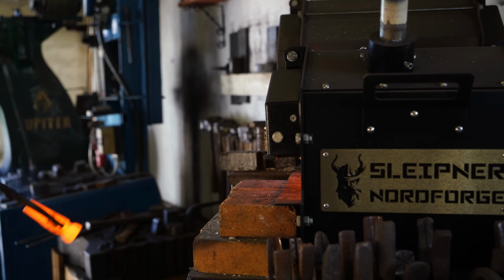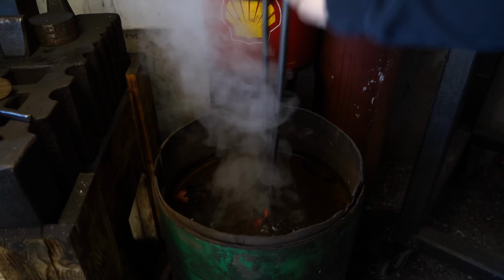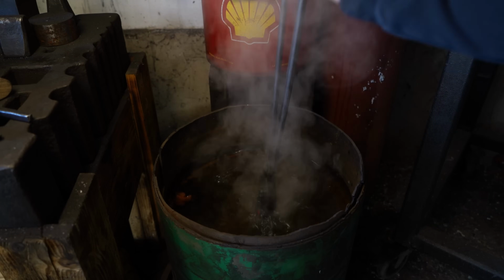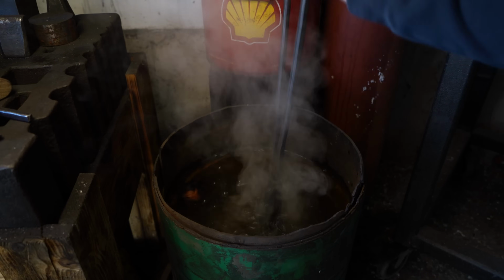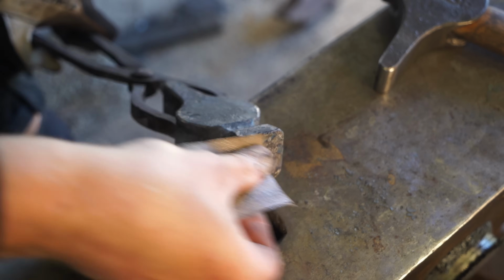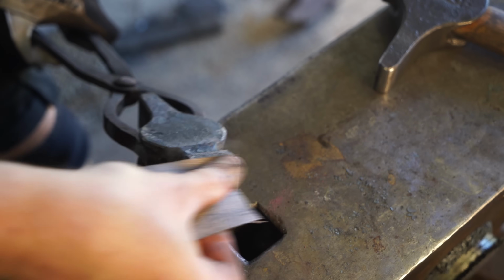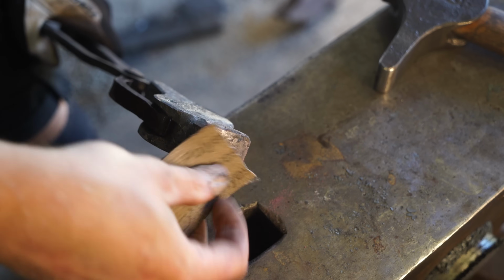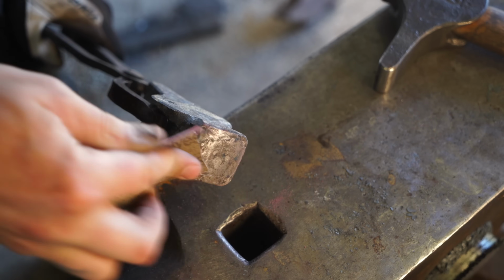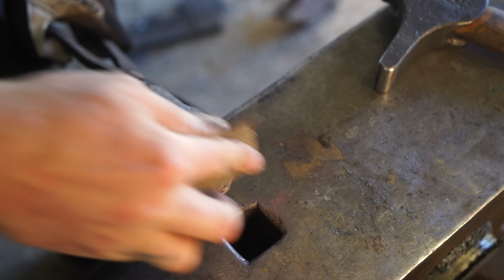The steel that I am using is a water-quenched steel, so I quench it in water and then I take it out and I use sandpaper to slightly touch the face of the hammer so that I can see bare steel. That way, during tempering, I can look for the color change in the steel to know at what temperature I'm at.